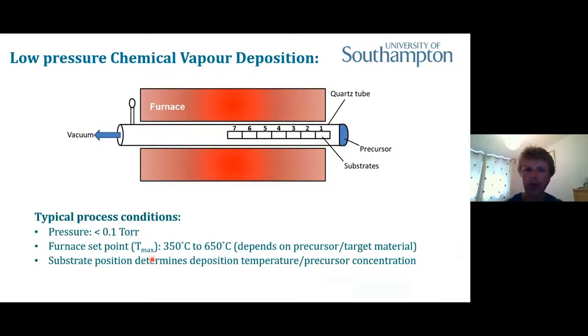A very simple graphic illustrating the sort of lab-based technique that we use for the deposition, for the low pressure chemical vapor deposition that we're working with. So this box here is a tube furnace effectively. We use a quartz tube which we insert through the furnace. At the far end on the right here, we would place the precursor in a little precursor bulb, and then we would place our substrates along into the hot zone. We connect this up to a vacuum system so that we can take the pressure down to around 0.1 torr or maybe a little bit lower. And then we can adjust the temperature to achieve the deposition, obviously dependent on the precursor and the target material that we're working with.